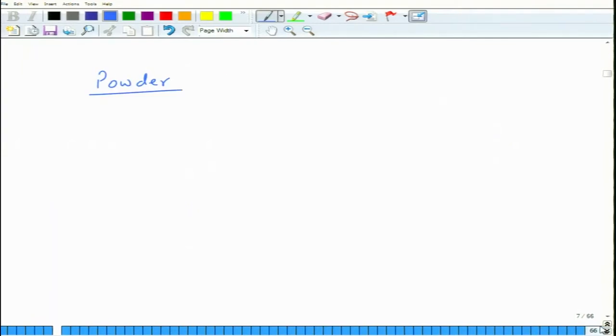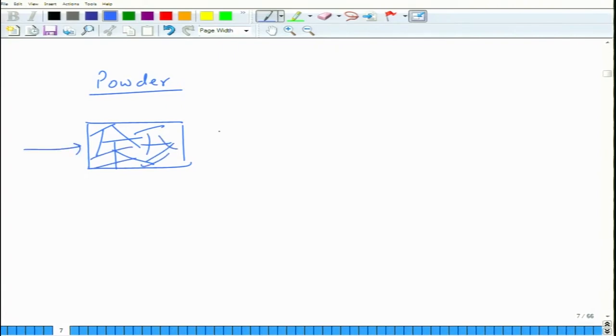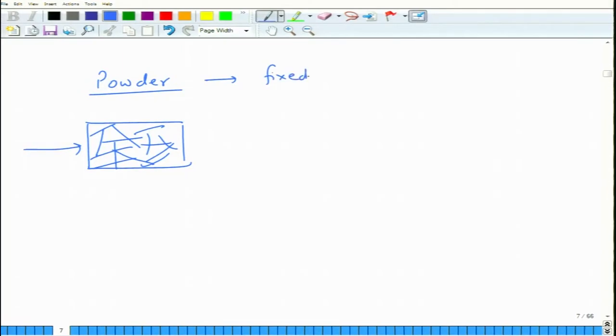However, in case of powder specimens, if you have a bunch of powder, one HKL might be like this, another HKL might be like this, another HKL could be this, another HKL could be this, another HKL could be this. So, you can have multiple orientations of HKLs. So, when the beam comes, it will always find some plane for diffraction which is oriented perfectly according to Bragg's law. So, for powder specimens, we generally use a fixed wavelength, okay. So, lambda is fixed